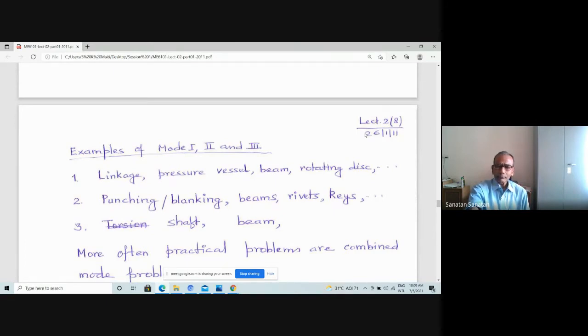Rotating disc: think of a rotating disc, the grinding wheel or any high-speed shaft. Just think of a thin sheet rotating. Obviously, the centrifugal forces are trying to develop stresses both in the circumferential and radial directions. So if you have a radial crack in a rotating disc, then the tangential, circumferential stress is going to open up that crack. So that is actually mode 1. So therefore, all that in the mode 1 crack example is there.